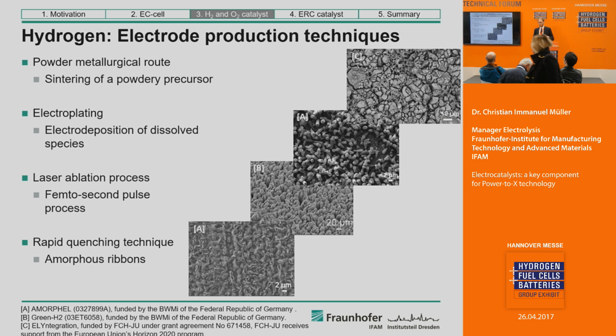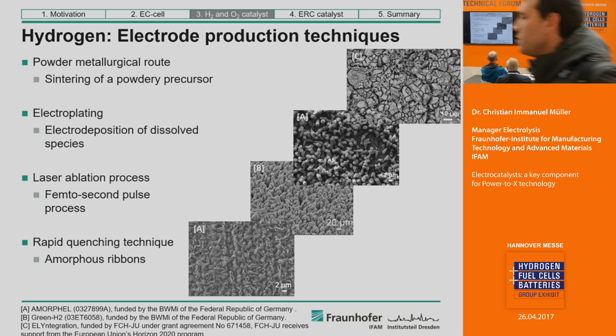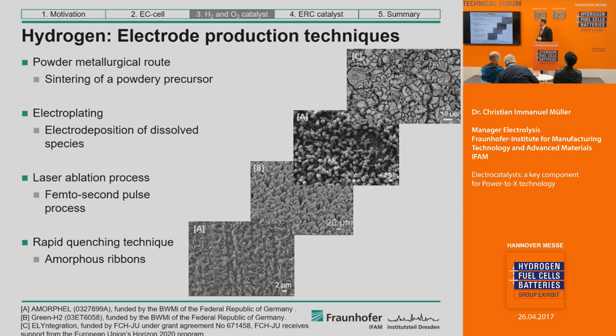Also, it's very important if you want to develop electrodes that you have the right technique to produce it. So it should be a scalable production technique. We use powder metallurgy as one example, where we start from a powdery precursor, which is sintered on a flat surface or also on a porous surface. We can use electroplating, where you electrodeposit dissolved species onto your surface by varying your parameters, your composition of the electrolyte. You can produce flat surfaces, also structured surfaces.